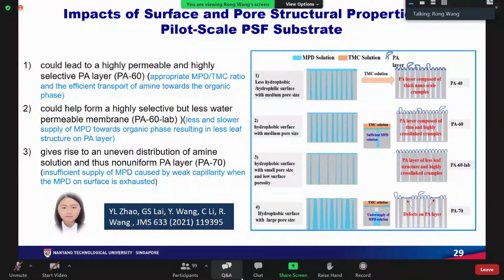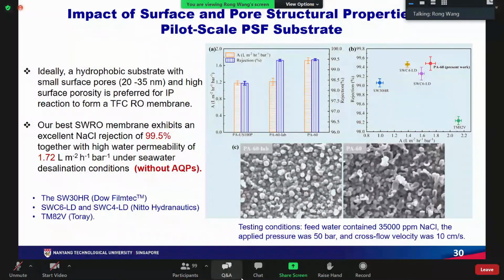And this work was done by Dr. Zhao Yali and the other team members. And this is the recent work published this year. We also found, ideally, a hydrophobic substrate with smaller surface pores and high surface porosity is preferred for the IP layer to form the thin film.